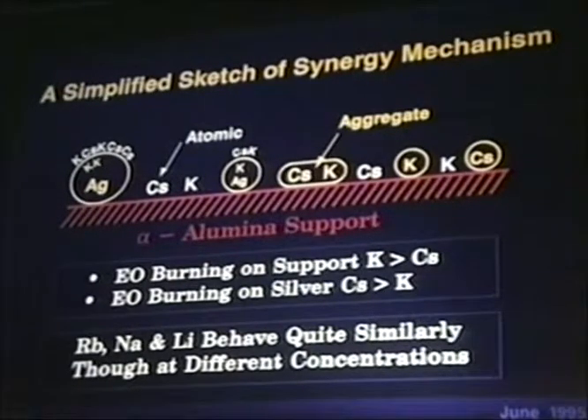We believe that likely both mechanisms are operating, in a manner that the mixed alkali synergistic catalyst is hence better than the best of the individual promoters, cesium. Rubidium, sodium, and lithium behave quite similarly, although at different concentrations and to different degrees of effectiveness.